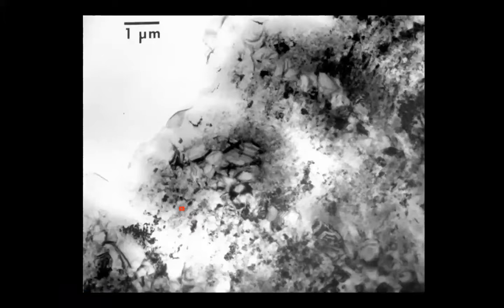So that almost atomic scale micrograph is outlined by this red box that you see on my TEM image here at lower magnification. And in this image, you see coarse-grained quartz crystals, fine-grained quartz crystals, coarse-grained quartz crystals, fine-grained quartz crystals. And so that kind of alternation between dense Brazil twins and less dense Brazil twins is all embedded within this fine-grained region that you see here. Now, this is the iris banding, by the way. This is the banding that is separated by a couple microns and scatters light and produces that beautiful iris effect. We're going to step back again in magnification.